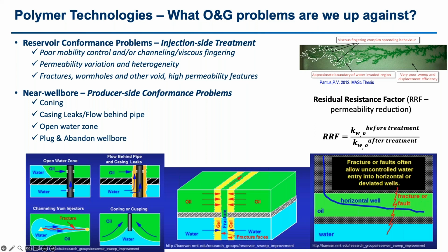Next slide, please. So this just describes some of the problems that we're dealing with. As I mentioned, most of our applications with MeriSeal are going to be for reservoir conformance. These are injection side problems, whether they're fractures, high perm voids, or maybe viscous fingering, but we're trying to fill and improve the sweep efficiency from the injection side. But obviously from the producer side, we have problems as well. This could be coning into the well, casing leaks or flow behind the pipe. Maybe we've drilled into an open water zone or fracked into an open water zone, and now we want to stifle that water production. Or in the more extreme case, we want to actually plug and abandon the well. So with the initial technology, MeriSeal, we're looking at whether we can potentially treat the well first and bring it back on production, and if not, then fully abandon it. There may be some opportunities there where wells are prematurely abandoned without fully extracting the oil resource.